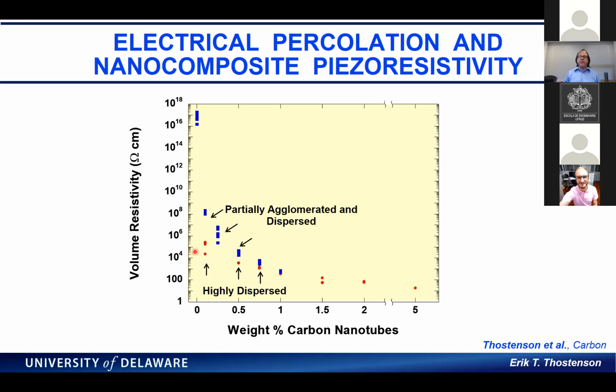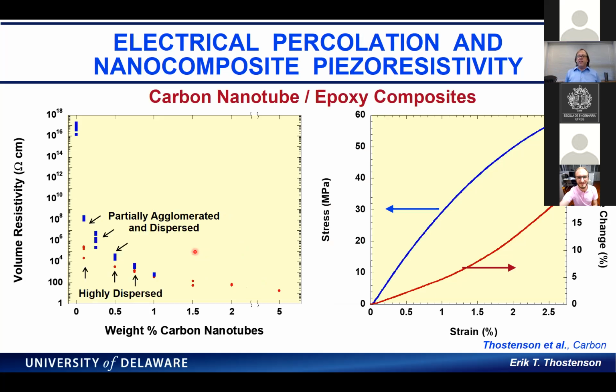And when I was doing these measurements, I had written some software, and I started bending and twisting the specimens, and I saw the resistance and the resistivity change quite remarkably. And so this is what we talk about in terms of once you're above electrical percolation, these nanocomposites become piezoresistive, in that when we strain them, the resistance changes more than we expect, simply based on a Poisson contraction and a change in length.